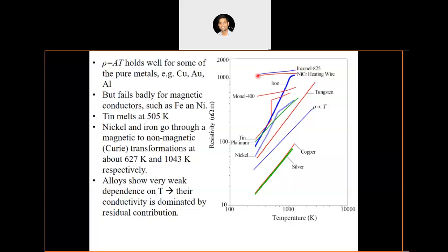That's why, although their resistivity is very high, right? Because it is coming from the impurity scattering. It is not dominated by the atomic vibration scattering or lattice scattering. That is why their temperature dependence is very weak, but their resistivity is very high, right? So these were the points which we have discussed so far, and we can see that those are followed in the experiments also. We can see these trends which we have derived so far using the theory, basically using the Drude model and the concept of scattering.